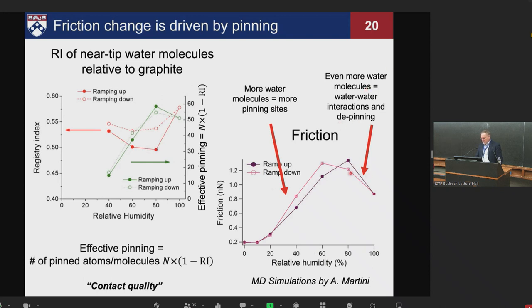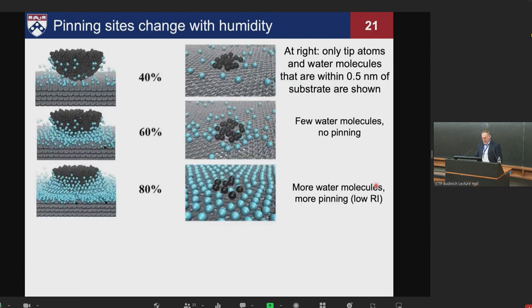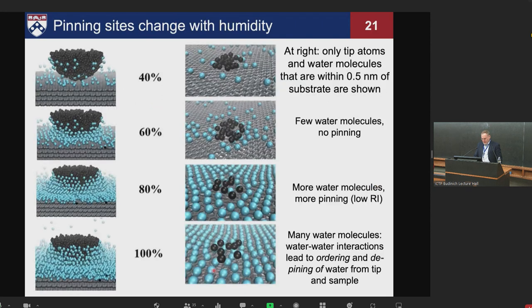What is happening here that's bringing it down? This is depinning. The water molecules, as you can see here, once you get to high humidities, 80, 100%, start aligning with each other. You have lateral ordering of the water at the interface instead of being disordered. And that gives you now essentially an incommensurate layer. Those lateral interactions between the water molecules allow it to create a layer that is now incommensurate with the graphene and with the tip, and allows easier shearing.